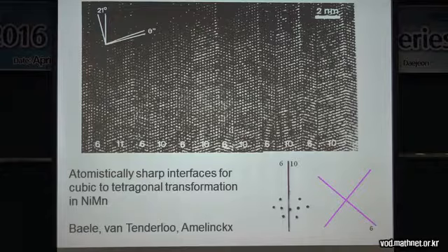And if you look at some part of the specimen, you'll see this piecewise linear deformation. If you run your eye across from left to right, you see it's linear in each of these layers. And the layers are alternately about 6 or 10 atomic spacings wide. So very, very fine layers. And each dot here represents a column of atoms perpendicular to the screen.